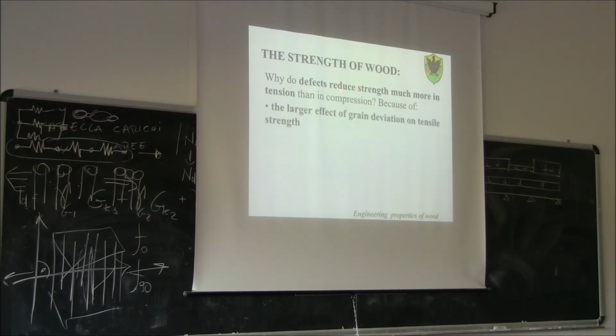Now, why do defects reduce strength much more in tension than in compression? There are a number of reasons. First of all, there is a larger effect of grain deviation on tensile strength. Those plots here show the dependency of the tensile strength of wood on the grain deviation. The second one shows the dependency of the compression strength of wood on the grain deviation. As you can see, the two curves are different. The first, showing the tensile strength, is much steeper at the beginning, so it's much closer to, let's say, bilinear. The second one is much more gradual, it's much closer to a simple line.